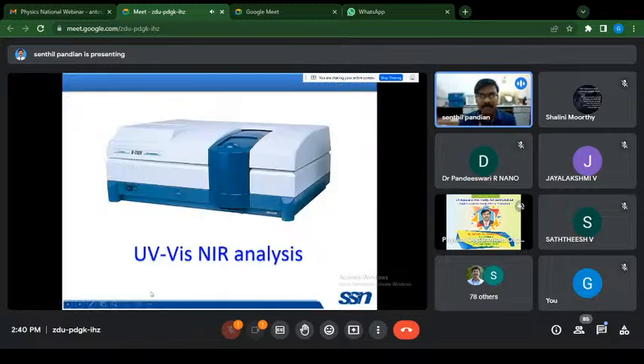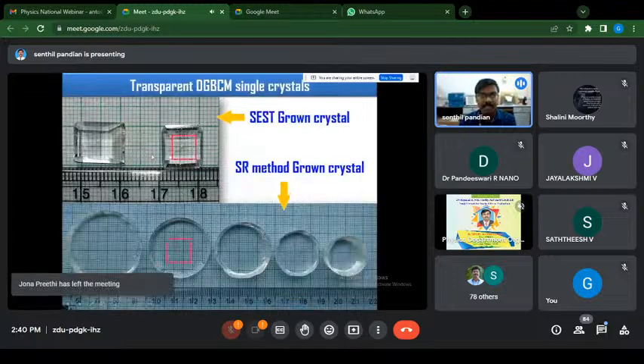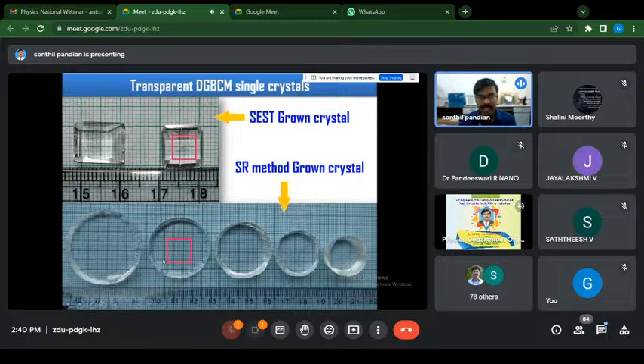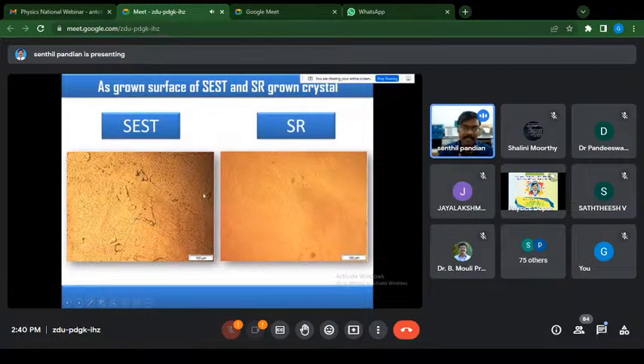The optical quality of the grown crystal is identified using this UV-Vis-NIR measurement. This is the transparent conventional method grown, diglycine barium chloride monohydrate single crystal. This is the SR method grown single crystal. You see, both are very transparent, but the microscopic picture clearly shows a lot of roughness in this SEST method grown crystal because of the large dislocation density, HB density, more microcracks, milky opaque regions in the SEST grown crystal. But in the case of the SR method grown crystal, there is less HB density, no solvent inclusion, no microcracks. So the surface of this SR grown crystal is smooth, comparable to the conventional method grown crystal under identical optimization.